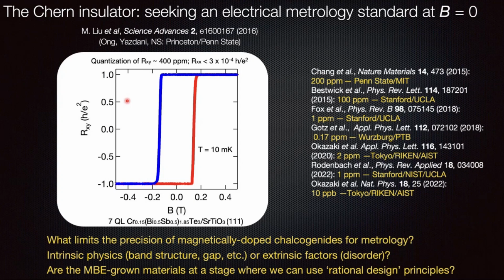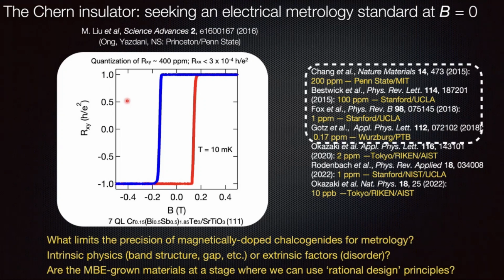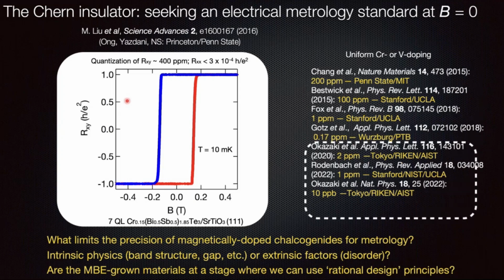Here I've listed on the right-hand side, and again, it may be that I'm not aware of some of the very recent work, but there was a lot of focus at Stanford, PTB, Würzburg, and in Japan on doing metrology with these chromium or vanadium doped bismuth antimony telluride materials. And then the Japanese group figured out that instead of uniformly doping, you could make modulated structures. They use the unfortunate term of modulation doping.